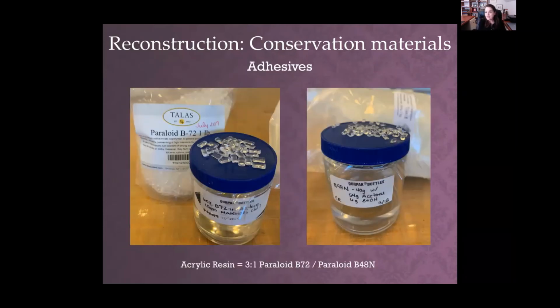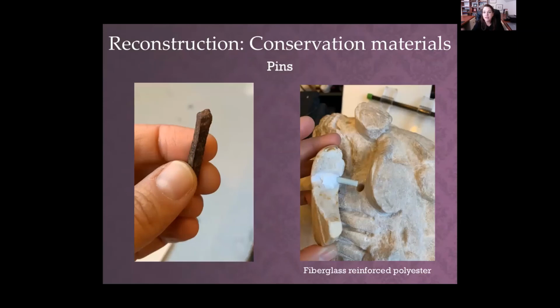So for the adhesives, we used acrylic resins, a 3:1 Paraloid B72 to Paraloid B48N. The adhesives are chemically stable, meaning that they will be reversible in the future. They won't yellow over time, and they have a good strength and minimal creep. So the creep would be the heaviness of the marble pulling at the join and having it move. The pins, as you saw in our gamma ray photographs, there are pins and clamps and all kinds of things inside of Bacchus.